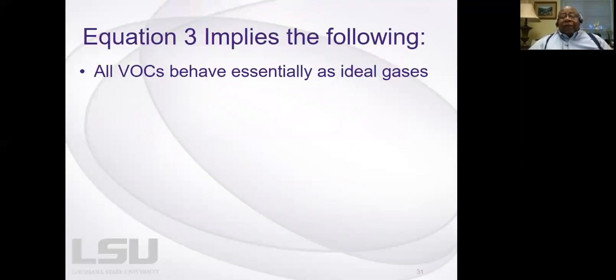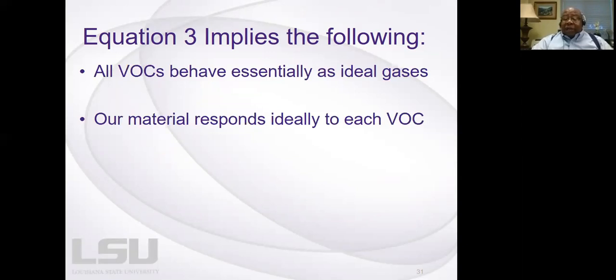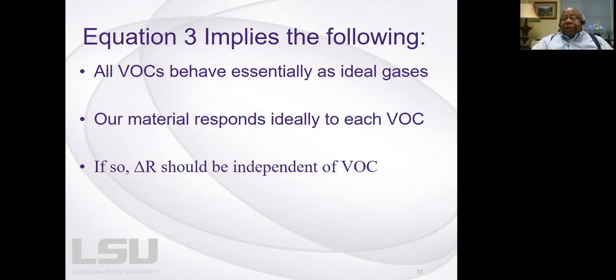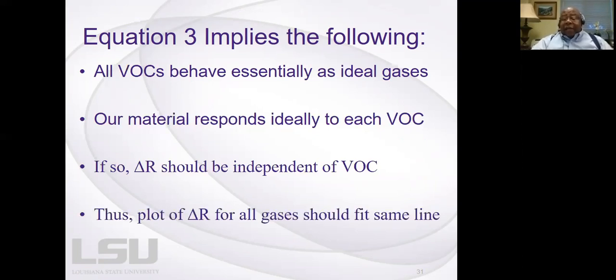So equation 3 implies the following, that we're using all of these different gases, so they must behave essentially as ideal gases. Otherwise, this relationship should not be true, right? Because we're getting something that is an ideal parameter, the molecular weight. And so in order to get the molecular weight of these individual gases, these gases must be behaving in a very similar manner. So our materials respond ideally to each volatile organic compound. If so, then delta R should be independent of the volatile organic material. In other words, if I plotted all of these organic gases, they should fit the same line. Thus, a plot of delta R for all gases should fit the same line.